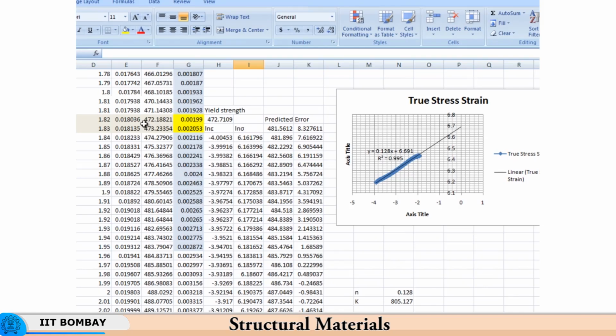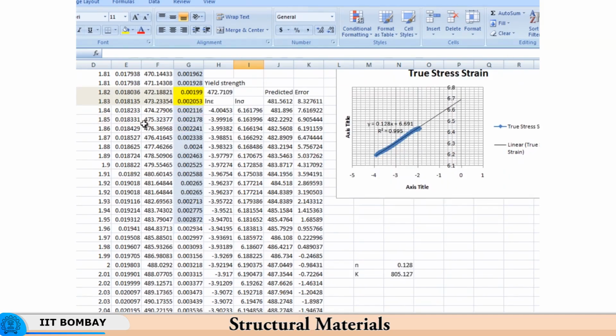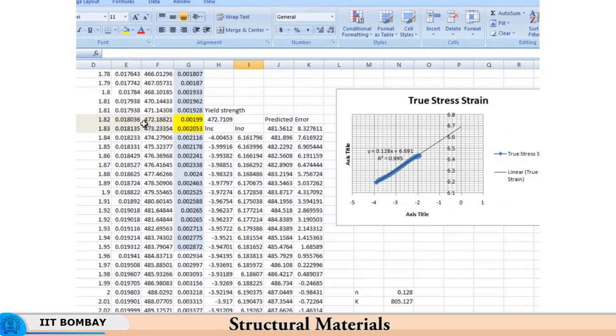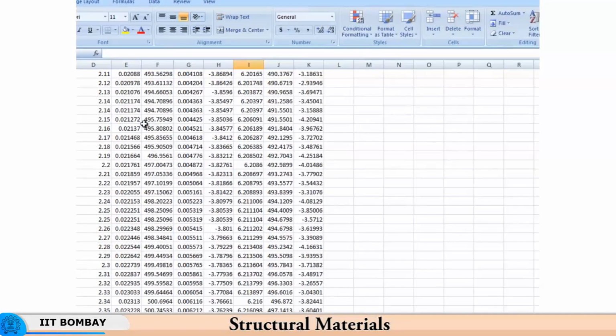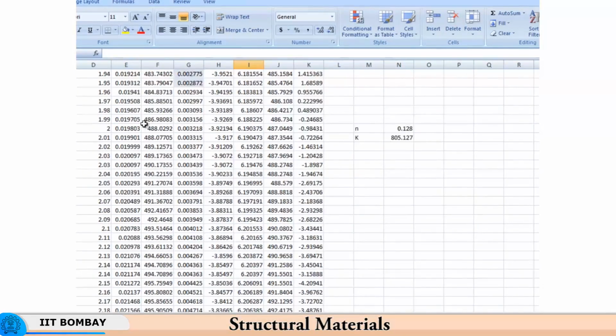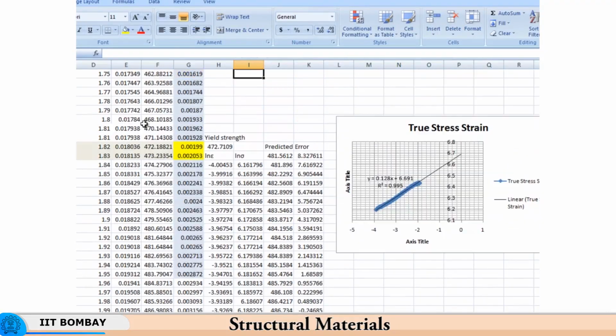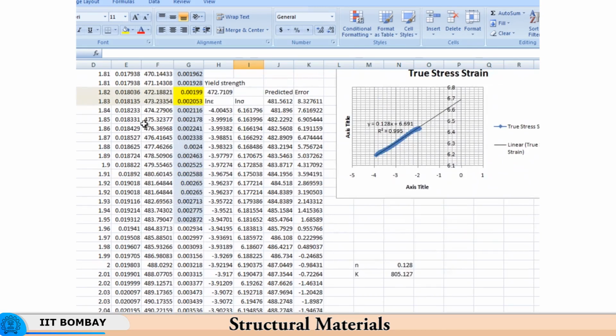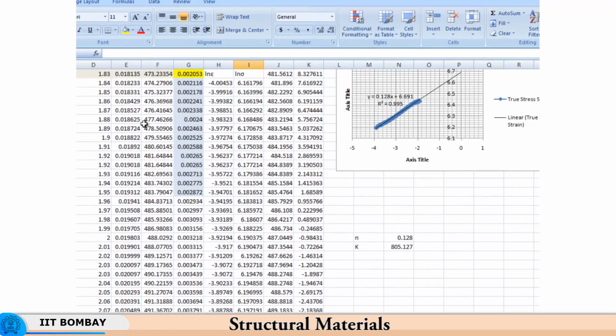So, I see that there is an error of about 1, and as I go down the error continues to decrease and then even becomes negative at some point. So, now I have a very small over prediction or under prediction by a few MPa. Now, if you look at the stress, it is about 476 MPa, the maximum error is about 8 MPa. So, 8 in 473 is a very small error which is tolerable, but then if you want to really use the equation sigma equal to k epsilon to the power n,